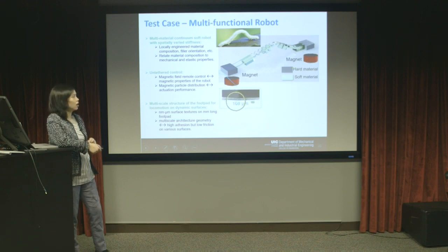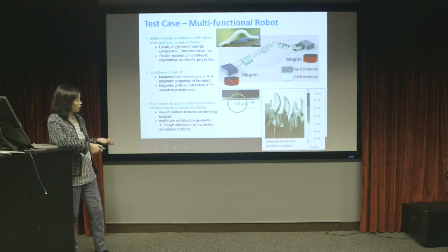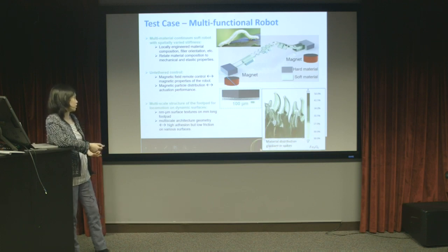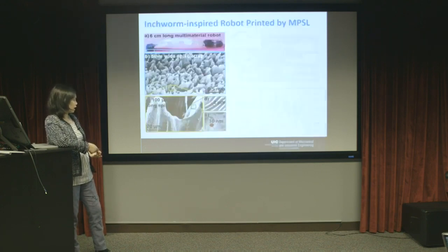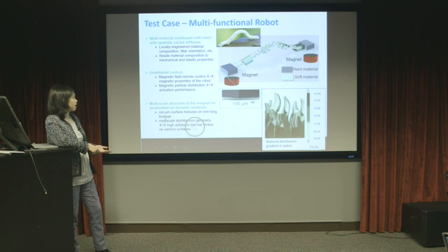In addition to that, for the anterior foot and the front foot, we want to have some spiked structures, such as shown here, something like the setae of natural organisms. For this small spike, the green part is shown here. If we look at the material composition in detail, we want it to have a gradient composition. The tip is more elastic, which means it contains more polymer, and the bottom is more magnetically responsive, so it contains more iron oxide magnetic particles.